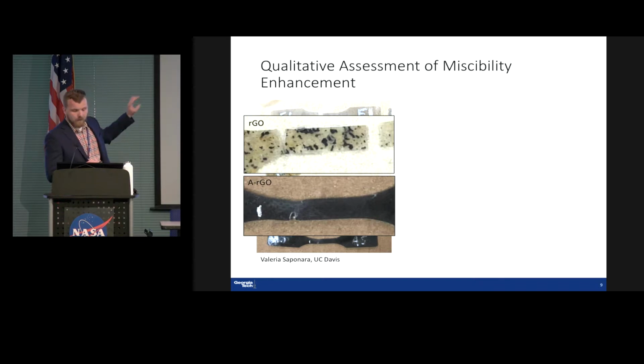In the reduced graphene oxide, where we have a lot of aggregation, we see complete failure, so it fractures. And then in the alkylated version, we see a different type of failure response, which is necking here at the, man, I don't know where I'm supposed to point this thing. But we see a necking response. So generally, this is what you think of when you think of a grocery bag, and you pull on it, it thins out, it turns white. That's actually the polyethylene crystallizing at this fracture site as the chains reorganize.